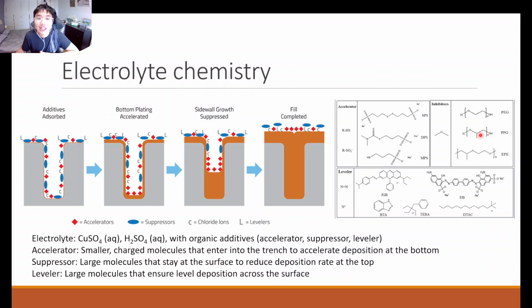And what about your inhibitors, also known as your suppressors? These, in comparison, are large uncharged polymeric molecules. Because they are large, they cannot easily enter into your trench, and so they loiter around the surface of your wafer. And because these molecules are large and also largely non-polar, they are able to block parts of your surface from the easy deposition of Cu2+ ions into copper metal. So it reduces the deposition rate of copper at the top surface of the wafer. This is to allow the trench to fill up first before too much deposition occurs at the surface of your wafer.